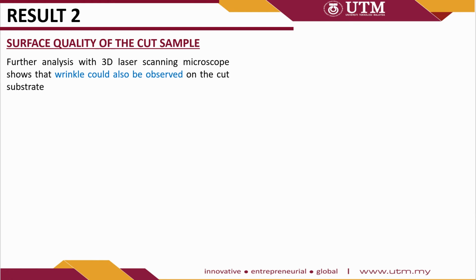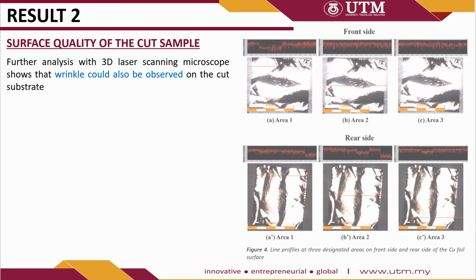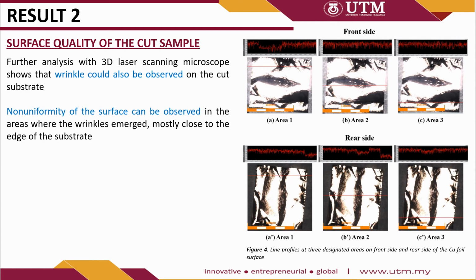Further analysis with 3D laser scanning microscope shows that wrinkles could also be observed on the cut substrate as shown in figure 4. Non-uniformity of the surface can be observed in the areas where the wrinkles emerge, mostly close to the edge of the substrate.